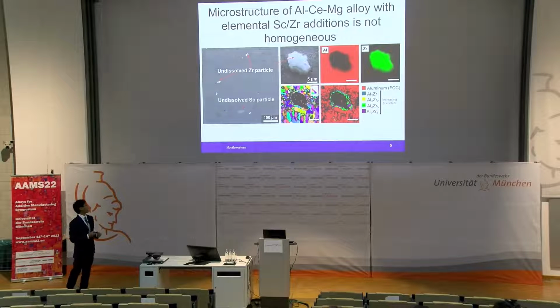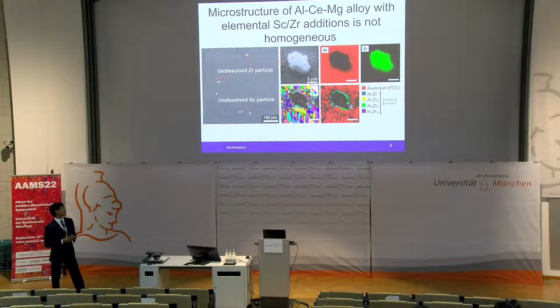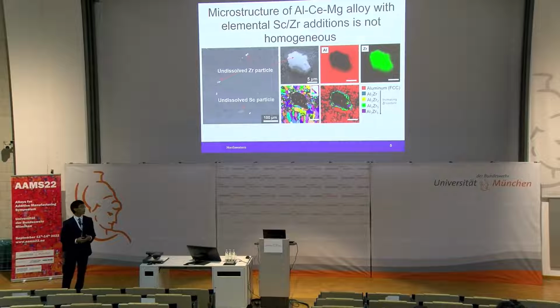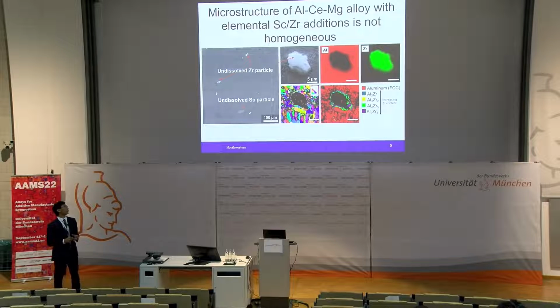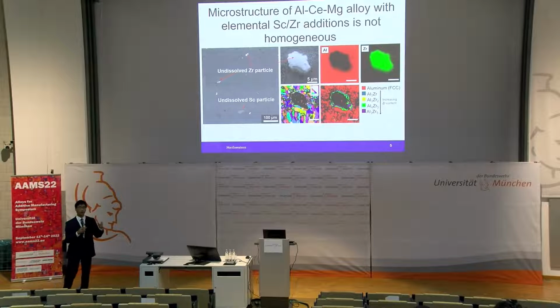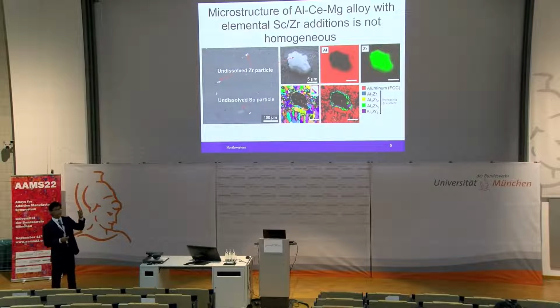We focus on one of these undissolved zirconium particles on the right, and we see from these EDS maps that it is indeed pure zirconium in the center with aluminum outside of it. And this indicates that very little dissolution has taken place during this laser powder bed fusion process. Interestingly, if we do EBSD around this particle, we see some local grain refinement, indicating that some zirconium must have dissolved such that the concentration of zirconium is high enough to form these aluminum-3-zirconium precipitates, which can then nucleate fine grains.